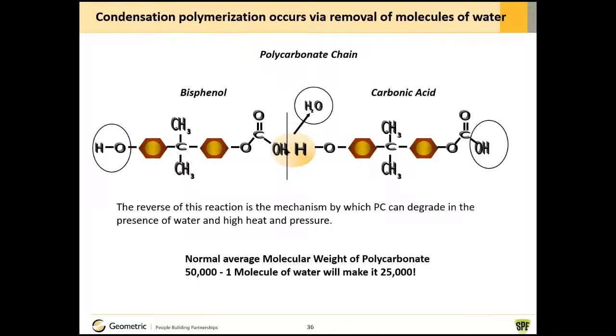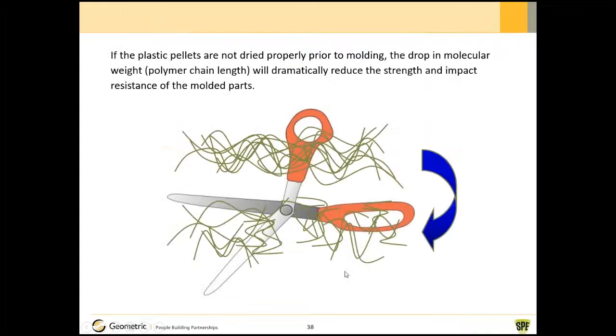Now, if you don't dry the material properly and there's moisture around when you're molding it under the conditions of high temperature and pressure and humidity, the water enters the chain again, and basically you take the 50,000 chain and the water molecule basically breaks it down into two chains of 25,000 each. And this continues to happen, and basically you take a pair of scissors and you cut up the chains if you don't dry the material. And it's going to dramatically reduce the strength and impact resistance of the plastic parts.